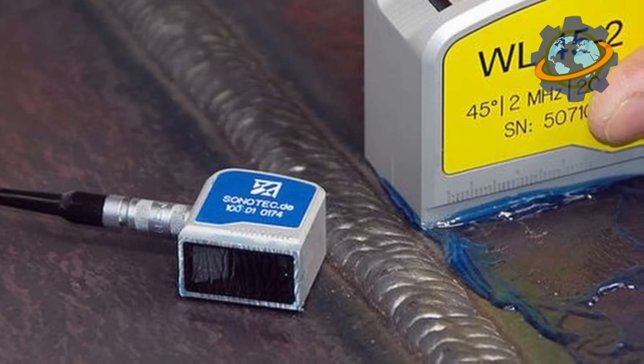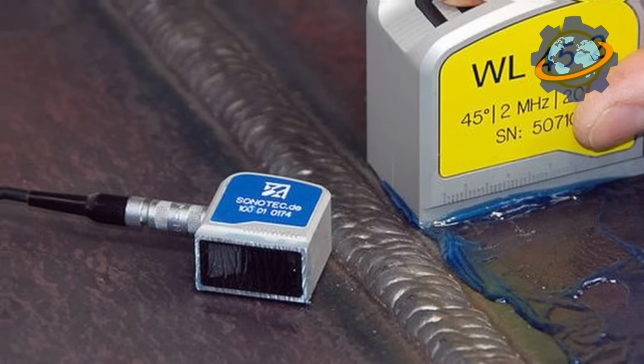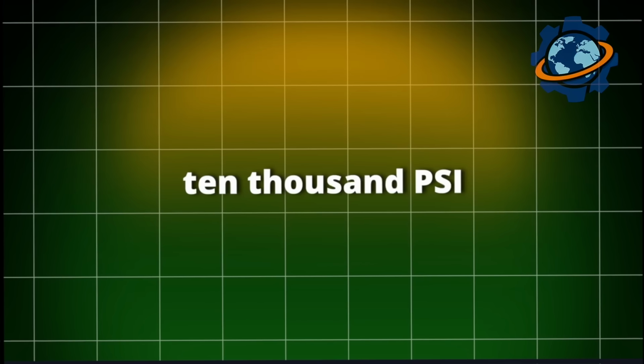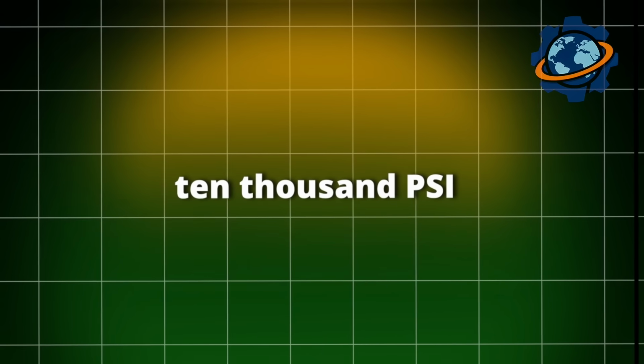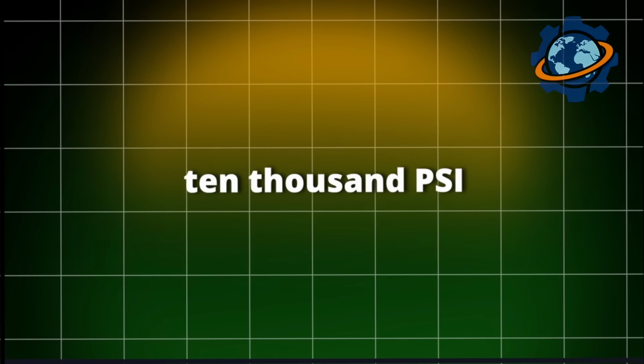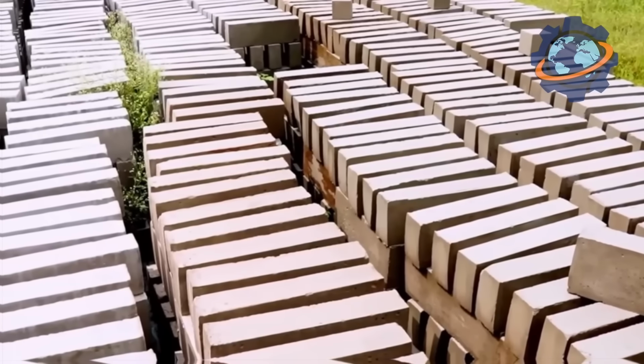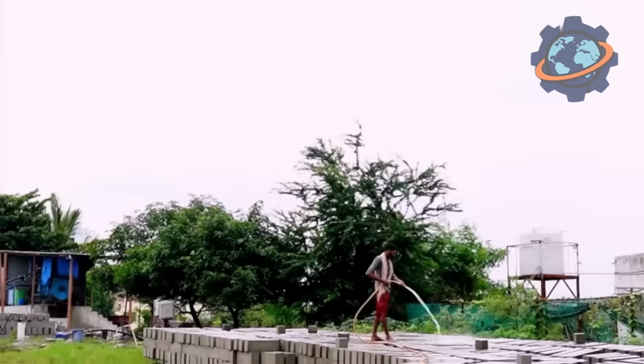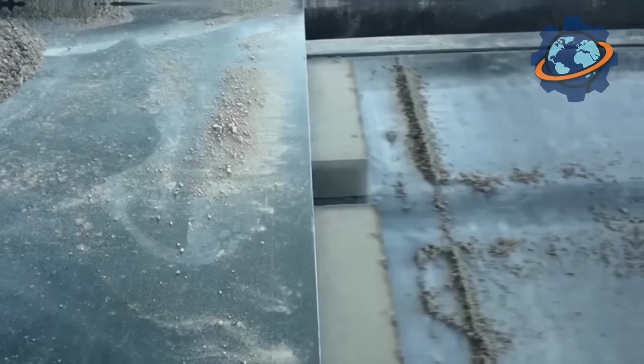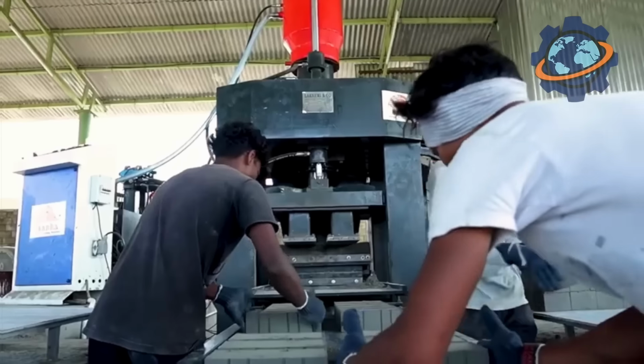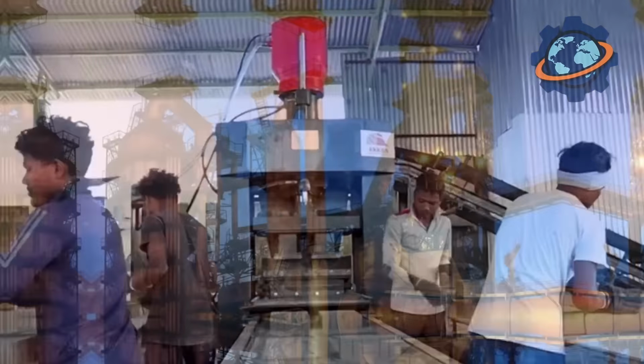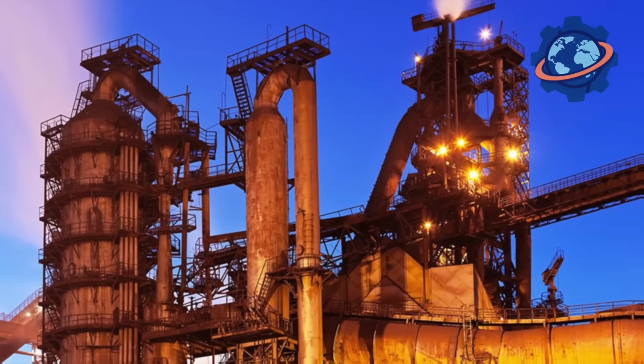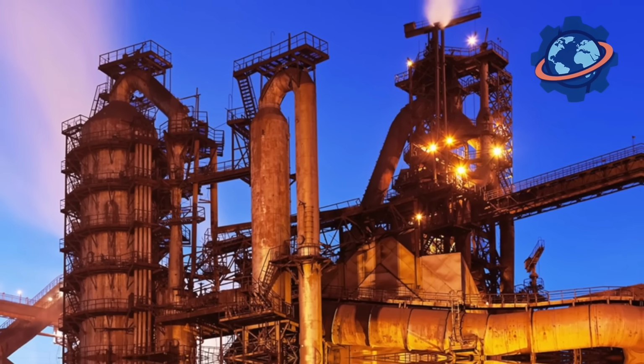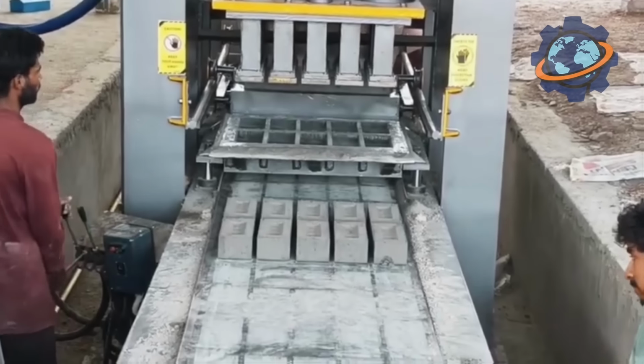Samples get crushed in hydraulic presses, measuring compressive strength exceeding 10,000 psi. Others get thermal shocked, heated to 2,000 degrees, then water quenched. Survivors prove they'll handle the brutal thermal cycling of industrial furnaces. Failure rate must stay below 0.5%. Even one weak brick can collapse a furnace wall, causing million-dollar shutdowns.